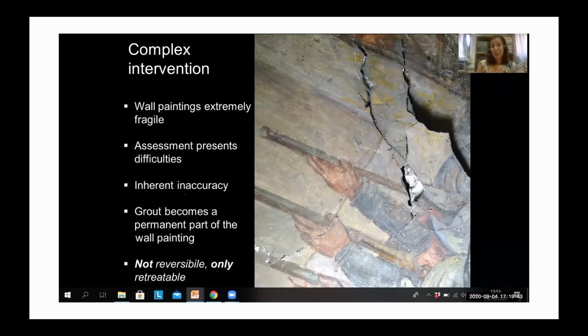And also, this is a very important point. The grout, when injected and when it's set, actually becomes a permanent part of the wall painting. So grouting is not reversible. You can't inject a grout and then remove it years after if, for example, the intervention was not appropriate, or if it failed. It's behind the layers. And so the only thing we can do is to retreat it, so to intervene again. But we can't really take out the grout from the painting, from the stratigraphy anymore.